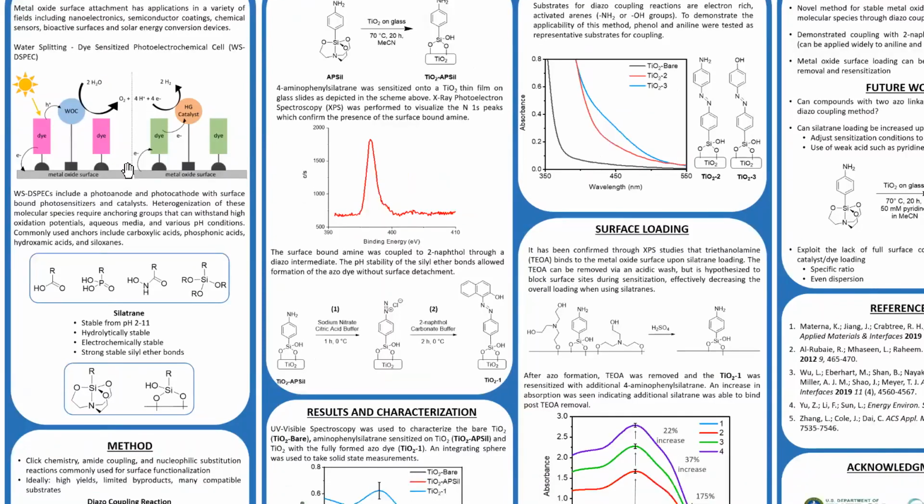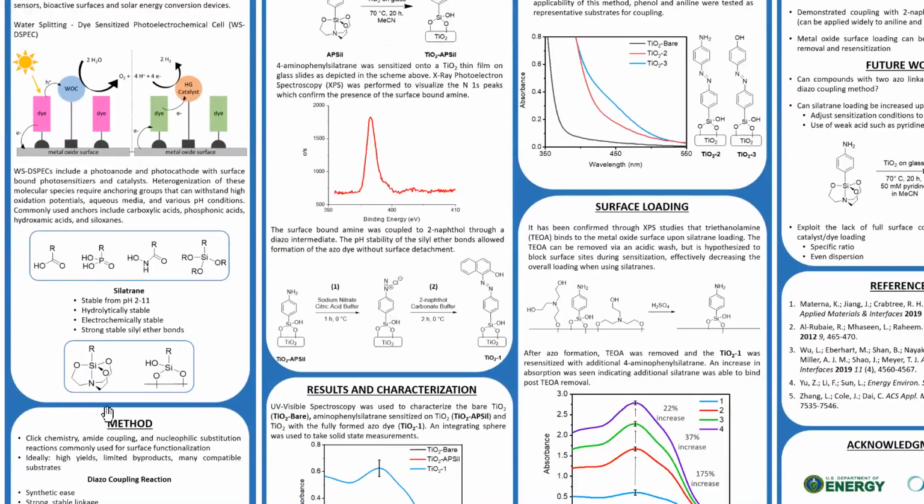This present work utilizes the silatrane anchoring group with its structure shown here, which is a triethanolamine protected siloxane. Not only does it form strong, very stable silyl-ether surface bonds, but molecular silatranes have a much longer shelf life than their unprotected counterparts due to limited hydrolysis and oligomerization.